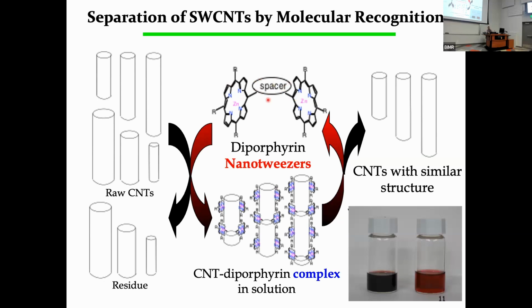And we can change the spacer to tune the distance of the two porphyrin units. Of course, we can tune the angle of the two porphyrin units. Then we define this cavity, and this cavity finds the appropriate structure of the carbon nanotube. Of course, they form a very stable complex like this. When it forms the complex and is dispersed in the organic solvent, the color changes from this porphyrin color to a blackish red color, including the carbon nanotube. Of course, some carbon nanotubes cannot form a stable complex, so they cannot be dissolved or dispersed in the organic solvent.